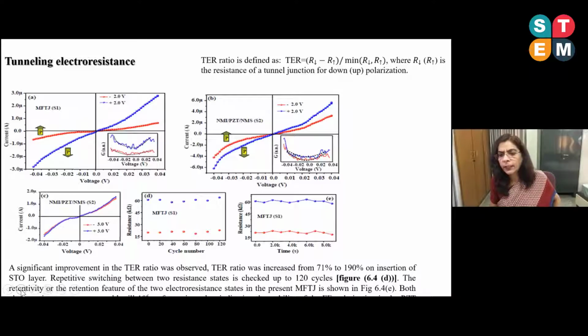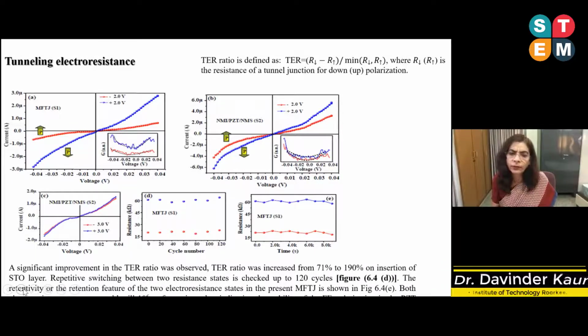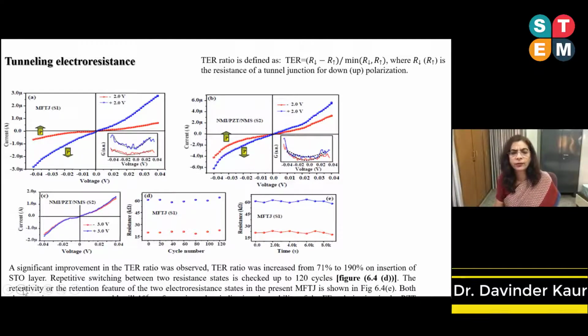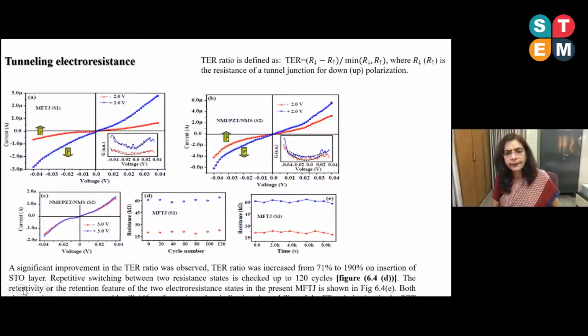So the TER value increases from 71% to 190% on the insertion of the STO layer. Repetitive switching between the two resistance states was checked up to 120 cycles for retention or retentivity. It shows that even after doing 120 cycles, we were getting more or less the same type of resistance.